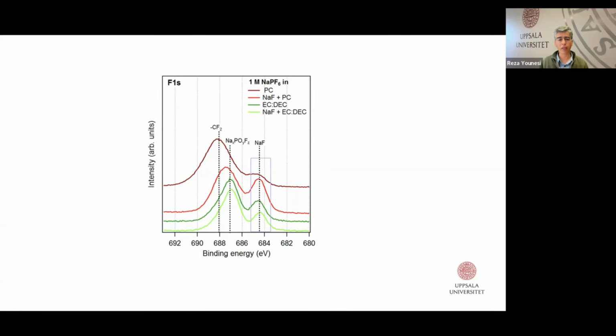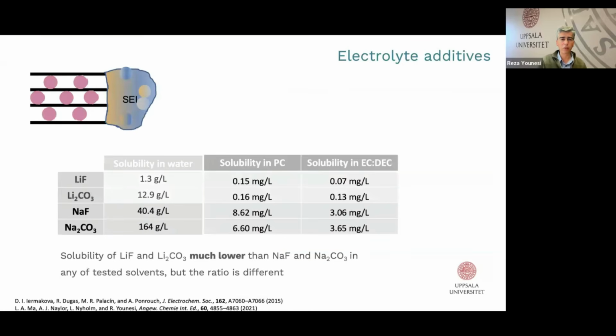We don't see much change when we add sodium fluoride in advance - basically the spectra and SEI composition is more or less the same whether we add sodium fluoride or not. But if you look at PC, the composition of SEI is influenced when we add sodium fluoride - there is more sodium fluoride in the SEI when we add it in advance. This is in line with the previous table I mentioned.